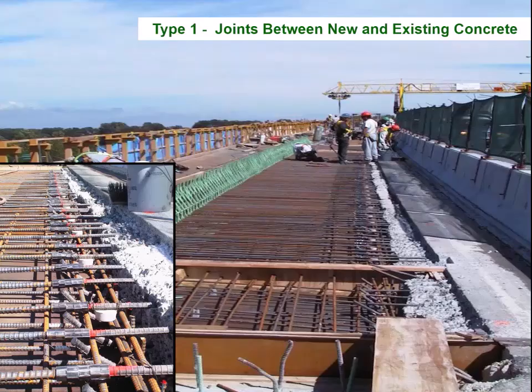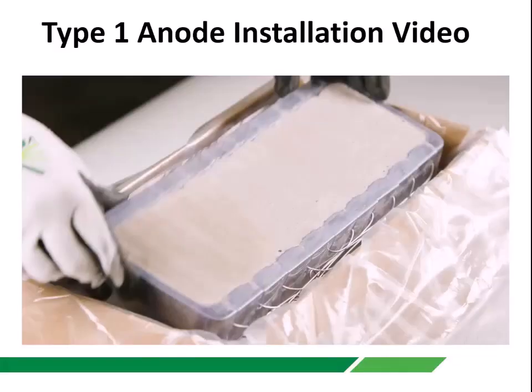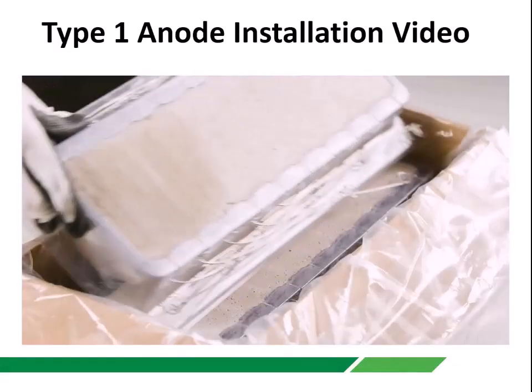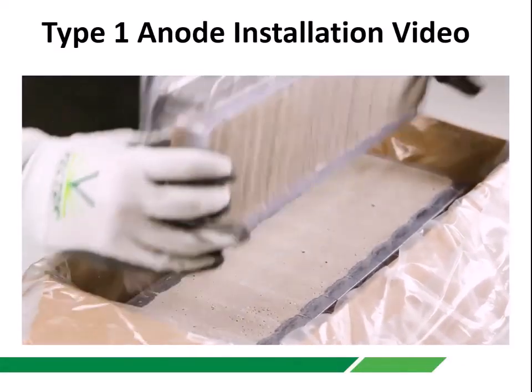If the old structure has been exposed for a number of years, say to chlorides or simply to carbon dioxide in the air, you will often have a potential difference between the two after this new concrete is poured. And so a line of galvanic anodes just along the interface is a relatively simple way of dealing with that issue. Okay, so just a quick video showing how these are installed in a repair.